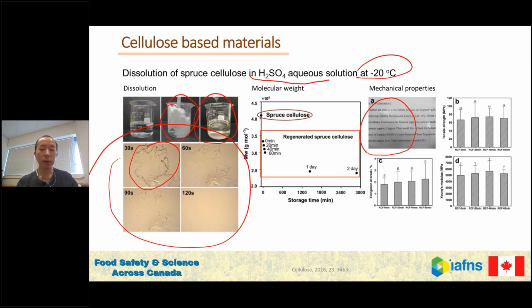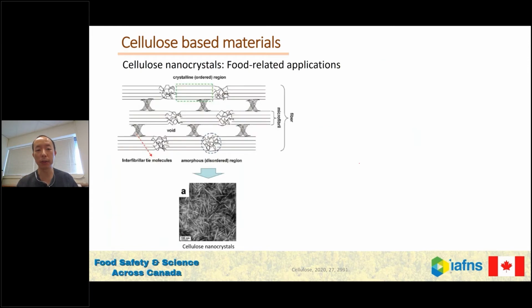And besides the dissolution, what else? We still have other methods to use those cellulose wastes. For example, we can generate nanocellulose from those waste materials. Nanocellulose is tiny particles like this. The length is about 100 nanometers. The diameter is about 10 nanometers. Actually, those nanostructures are synthesized by nature, by plants and animals. What we need to do is use mechanical or chemical methods to separate those nanostructures.